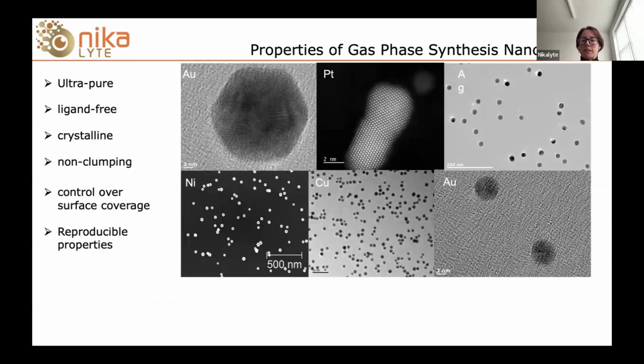So in this example, I've picked some very typical materials that we work with. The platinum group precious metals are commonly used because they form nanoparticles very readily and they're very easy to sputter, but they also have lots and lots of applications in life sciences and in catalysis. So you can see nanoparticles here for gold, platinum, silver, copper, and nickel. And what you'll notice from these lovely TEM images is that we've got really nice crystalline nanoparticles. We can see individual atoms.